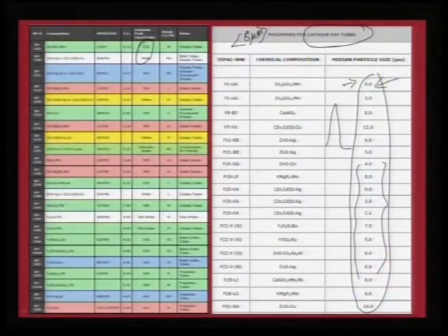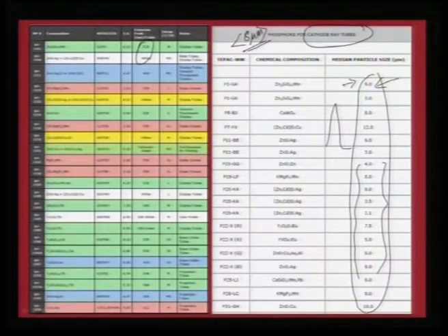Because we are living in a nano world, there is always a temptation for us to talk about nanometer, but one should also realize that the micron technology is proven and it cannot be shaken that easily. Therefore, when you talk about CRT, the issue is not about nano size, but about a very narrow distribution, and what is good for processing is an average range of 8 micron. So, if you have an 8 micron particle, you do not have to feel bad, but you can only be happy because that is exactly what is preferred for developing different panels.